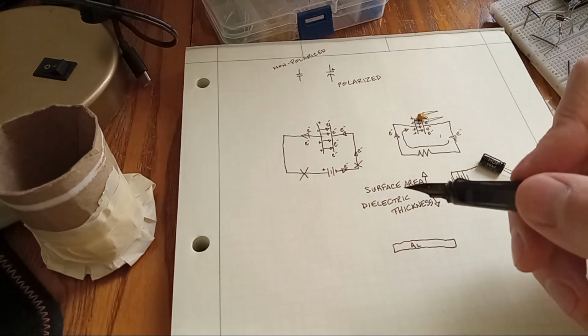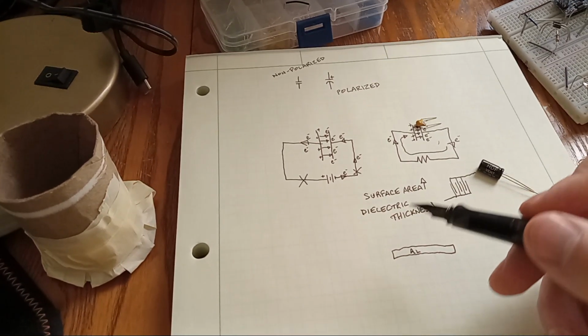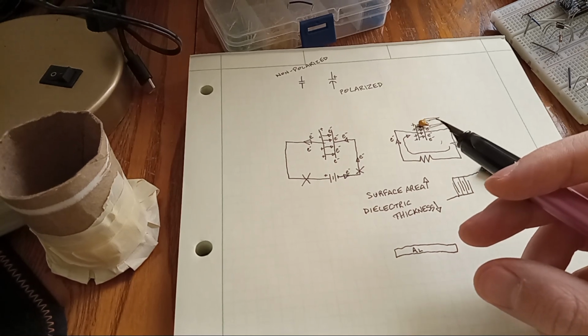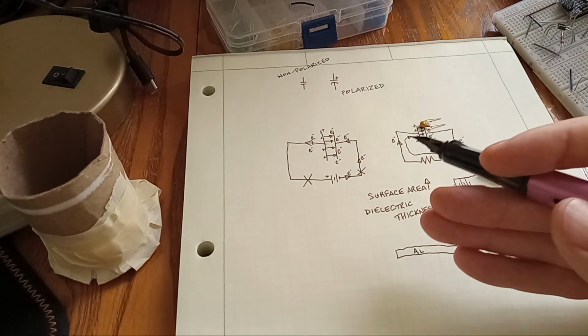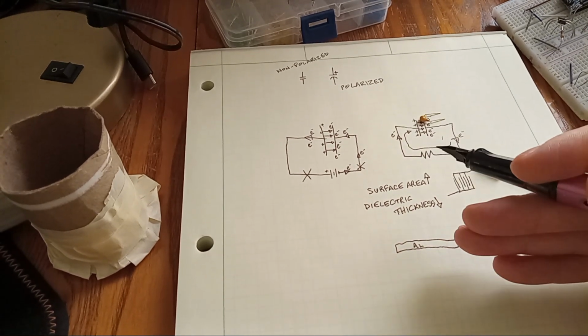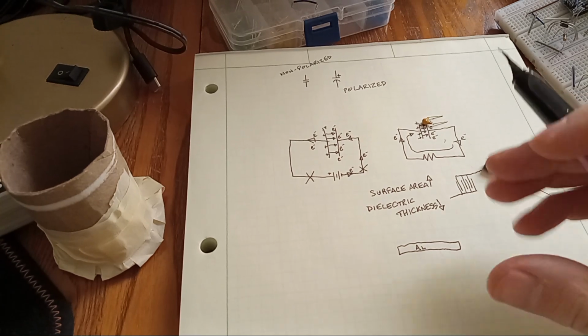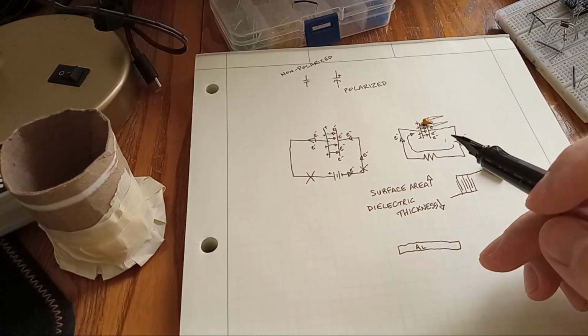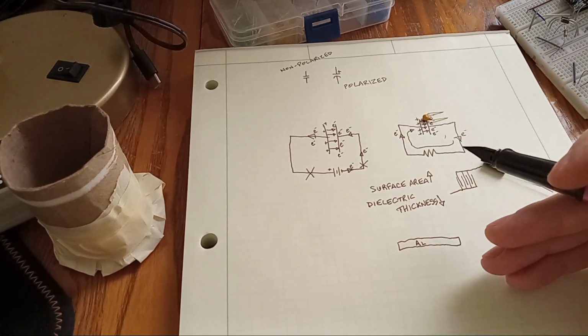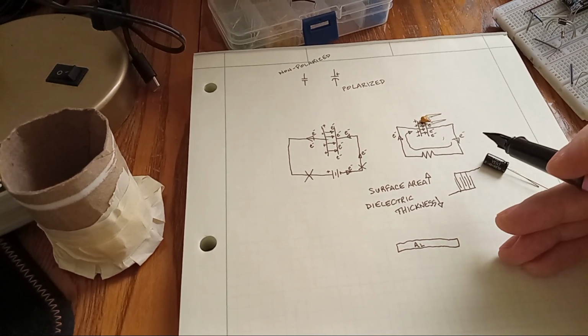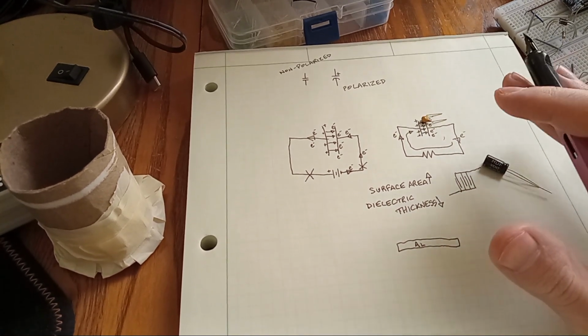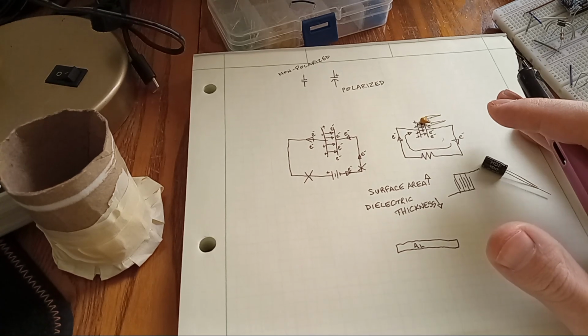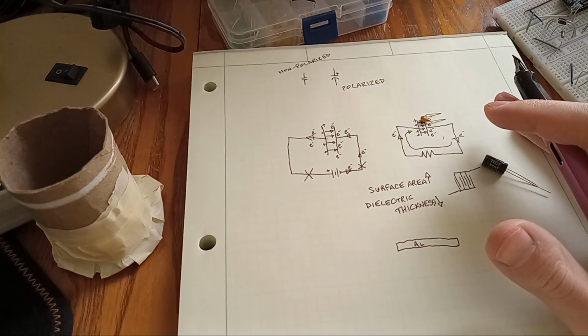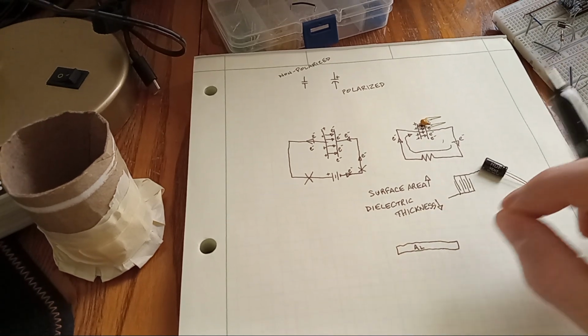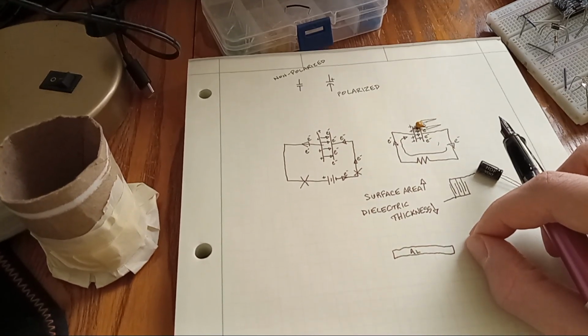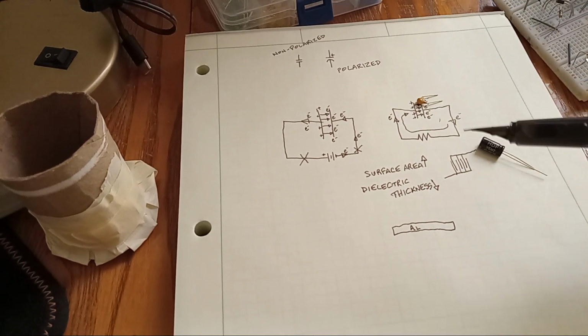It's also why aluminum house wiring can cause issues if you connect it to a not appropriately rated connector, because as the connector and aluminum wire expand and contract with thermal cycling, it forms a tiny gap which is exposed to the air, and then the aluminum grows a protective oxide layer which is non-conductive, so the resistance at that connection begins to increase. And because P equals I squared R, if you increase R, then the power dissipated increases, and anyway, it overheats the connector and burns down your house. So if you have aluminum wiring, make sure that you are connecting it to screw terminals and wire nuts and whatnot that are all specifically rated for aluminum wiring, or you'll have a bad time. Be very sad.